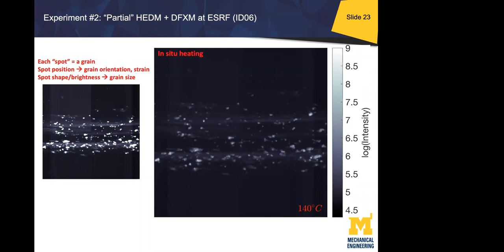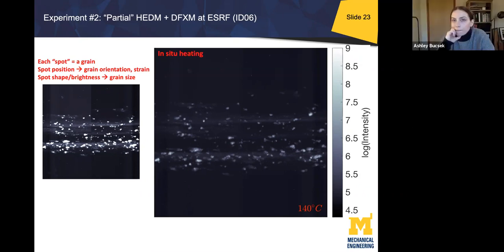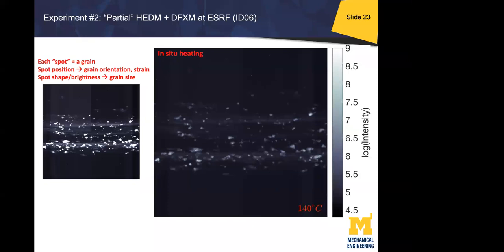So I've been working on an extension of that Sonia's work that you've shown, that partial HEDM. And we believe that, at the cost of some scanning time, you can travel your detector, or you can repeat the same scan you did for the full omega range. And just by patching the frames around the ring, we believe that we can actually recover a center of mass map of the deformed structure. We're still working on it. But in a few months' time, we may have a workflow that can produce some results.